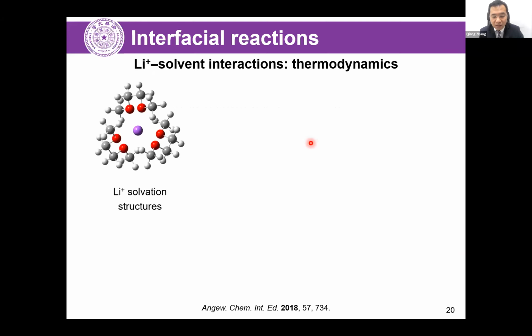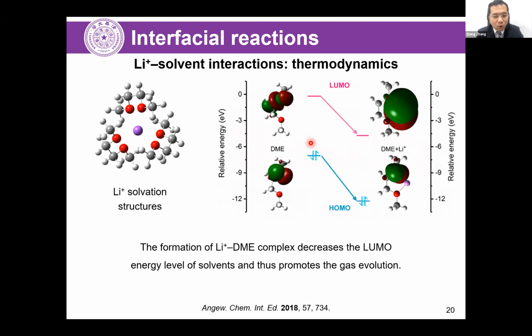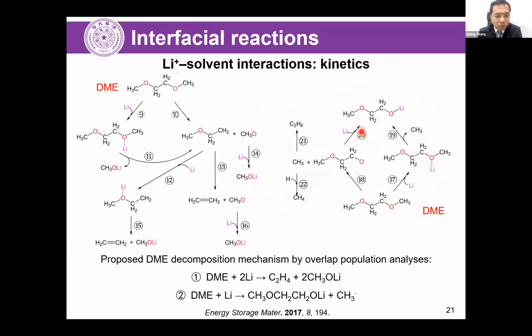So first, we try to probe what happened at the interface. The lithium metal anodes or the BCC crystal, and we try to combine them with some carbon host. Well, from the viewpoint of the electrolyte, it is found they are quite complex. The lithium ion in the solvent was not individually paired. It can be coordinated with the solvents and form an ion-solvent complex structure. Once the lithium ion coordinates with the solvents, it is found that the LUMO of the solvents can be reduced significantly. So in this case, it prefers to attract electrons, while the exposed alkali metal can provide electrons directly to the ion-solvent complex. So with this consideration, we try to probe what happened once the lithium ion takes one oxygen and then the electron transfers there.